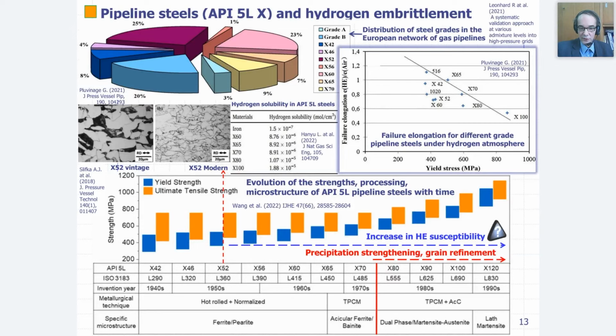these two microstructures. It's also important to mention that, for example, in the case of X52, we have a change in microstructure. In the case of vintage X52, we have a ferrite-pearlite microstructure, and modern X52 structure is elongated ferrite and acicular ferrite. So we have a different hydrogen solubility due to the difference in microstructure, and also a difference in permeability in different grades of pipeline steel, which finally define the hydrogen embrittlement susceptibility of a particular type of steel.